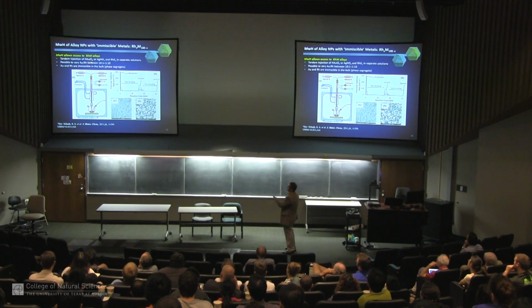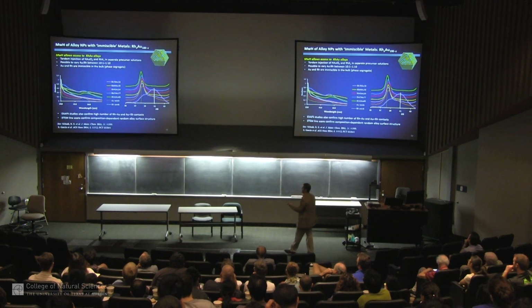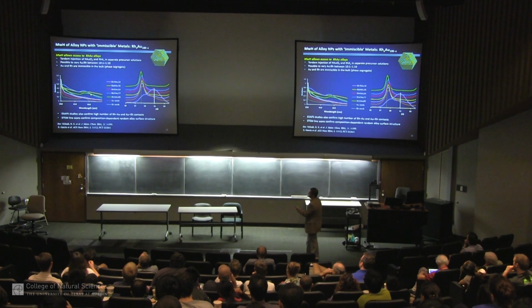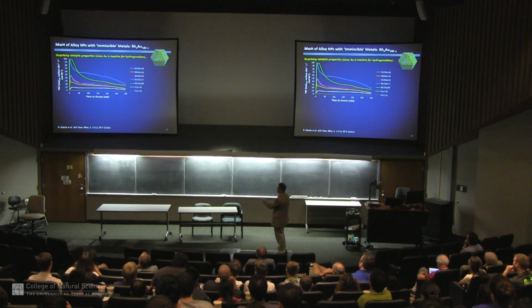We can also tune the composition widely just by the amounts of metals we add, and you get these amazing alloy particles. And so we started to do catalysis, and I realize I'm 4 minutes from time, so I'm going to skip through this characterizing data, but just to show the XRD shows a shift, and the surface plasmon behavior of these particles is unusual, telling you that there is a random alloy in mixing. So you take it from me that these are random alloys, they're not intermetallic and they're not ordered.